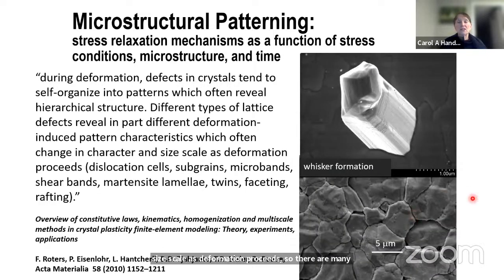So here's a picture of one tin whisker. And one of the things that's important here, and I have to tell you, this is my favorite tin whisker of all time. This is the original surface of the film. And so think about this as sort of the geologic time. This is how it grew out. So if you looked at it over time, each of these layers you would see happening as a function of time, and there's actually no diffusion, very little diffusion that happens in the whiskers themselves.